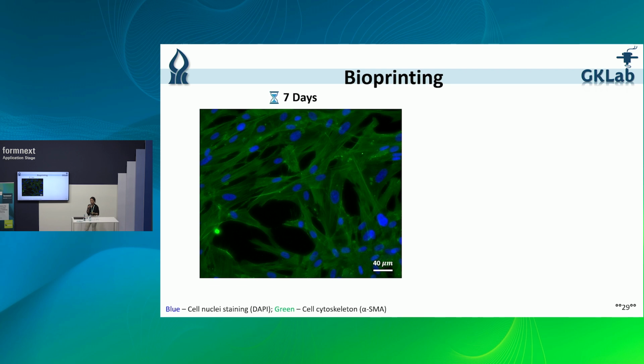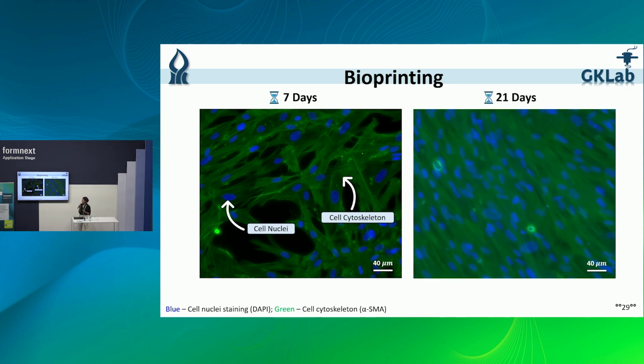So now I'm going to show you microscopic images of our cells after incubation. So this is an image of human dermis cells after 7 days of incubation. In blue, we see the cell nuclei, and in green, the cell cytoskeleton. First of all, after 7 days, we see that the cells are alive and well, meaning our bioink is not toxic, as we can assume. And now, after 21 days, we see the cells have multiplied significantly, and they create this kind of continuous tissue. So we see great promise for this bioink for skin bioprinting, and also in the future for further tissue applications.